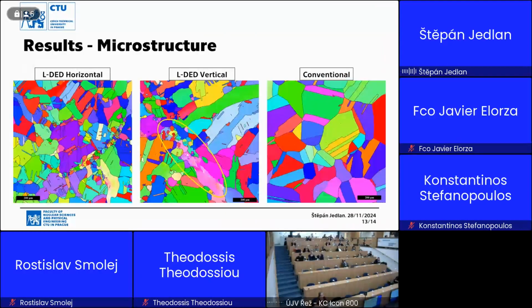And here are the results of the electron microscopy, the EBSD that was done, and as you can see, there are little areas where the 3D printed material is not completely recrystallized, and also the grains are a little bit greater in the case of the conventional material. The grains in the conventional material are about 5 times bigger, which resulted in the higher ductility and lower strength of the conventional material. And also you can see that the grains are still a little bit columnar and not equiaxed.